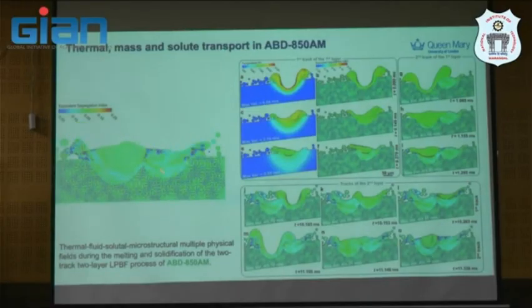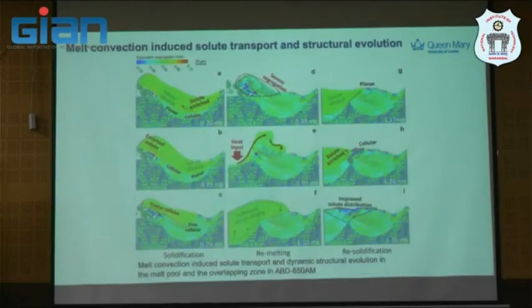So this is what happens in a multi-track, multi-layer deposition. We start with the segregation profile. You will see layers adding up. And then what you see here is a thermo-solute fluid flow model doing rapid solidification of a two-layer deposition. I want to highlight in the composition here that the solute actually enriches here once the second laser arrives. In the first layer, you leave behind an enriched solute zone and a solute dilute zone, and as solidification progresses, the cellular structure takes place. This is planar growth because we're talking about a high cooling rate, right?